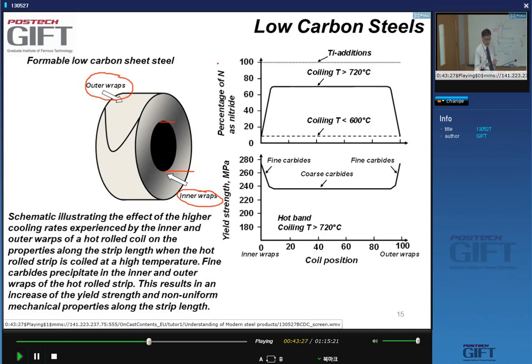So if you look at the amount of nitrogen that's precipitated when you have a high coiling temperature, you would expect that with a high coiling temperature, aluminum nitride should precipitate. What you see is that, in general, that is true, the nitrogen is precipitated, but not in the outer wraps and not in the inner wraps. Yes? And the same with the carbides. Yes?